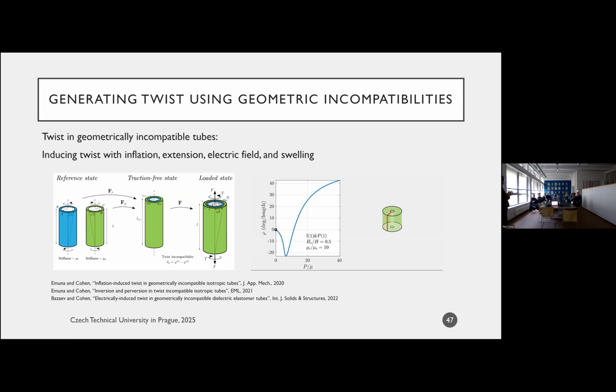It's not material anisotropy. The anisotropy is not associated with the material, but it's associated with the process. So it's a stress-induced anisotropy. And in this structure, because of the residual shear stresses that are stored in it, if I inflate it or stretch it, or if I take dielectric elastomers and apply an electric field to it, this is going to twist. And it's going to do some interesting things. So I'm going to show you a simulation that we ran on this structure. We've done a lot of different things with this, but I want to show you one simulation, right?